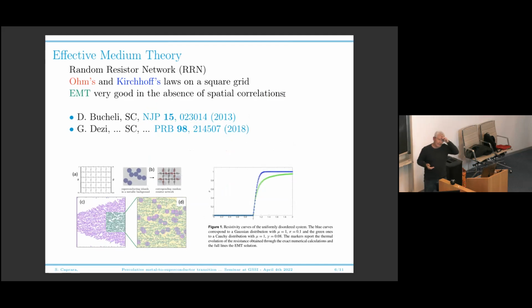And this is exactly what we did. This was a second stage of our research. After having dug into the physics of the effective medium theory approximation, we realized that to provide a better discussion for the physics of our system, we should go to a random resistor network. So now imagine that you map your system in a random network where you have, for instance, this square lattice, and all the bonds of the lattice are assigned a resistance. And this resistance is a finite value in the metallic state or zero in the superconducting state. Then you have a random resistor network.